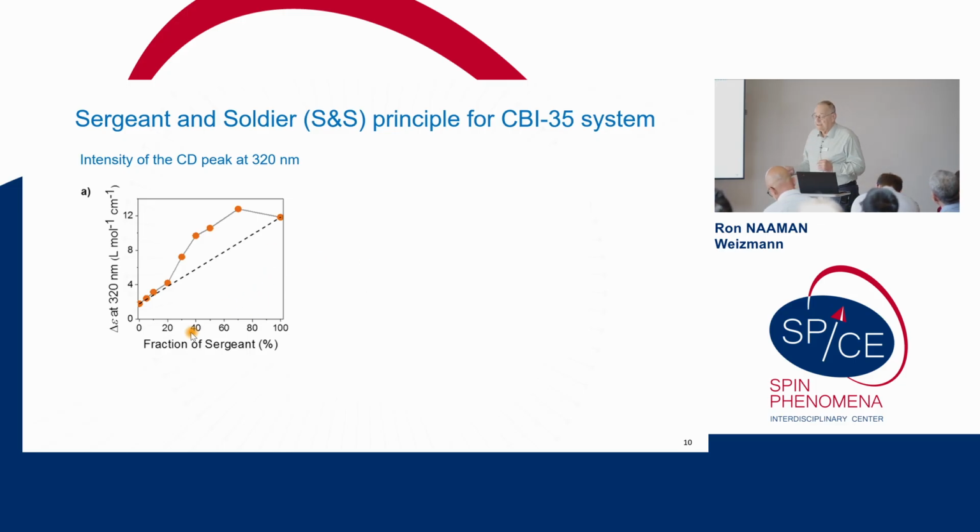And in Eindhoven, they did the measurement, and you see they doped the wire with the chiral molecules, the soldiers being the achiral molecules, and you see in the beginning the dependence of the optical activity is linear on the doping, but then there is amplification and it jumps.